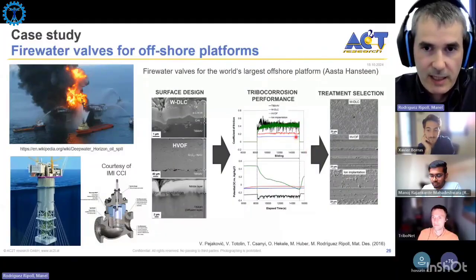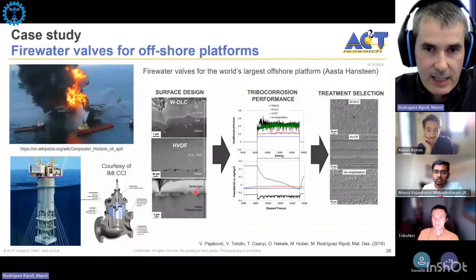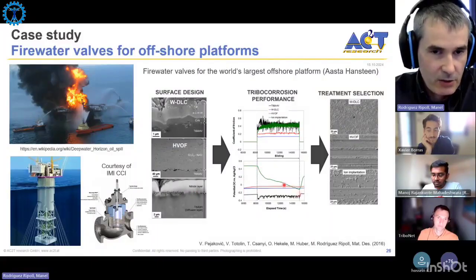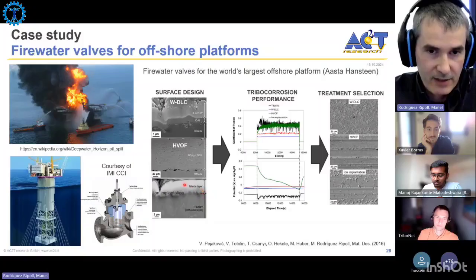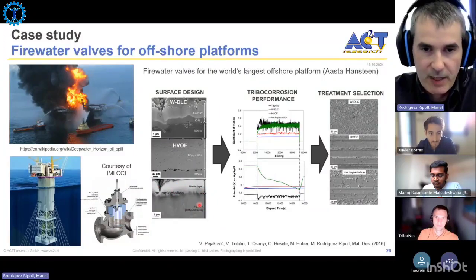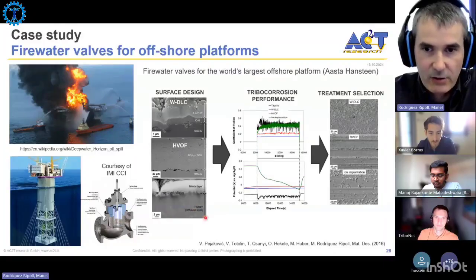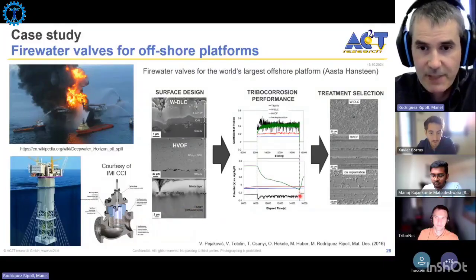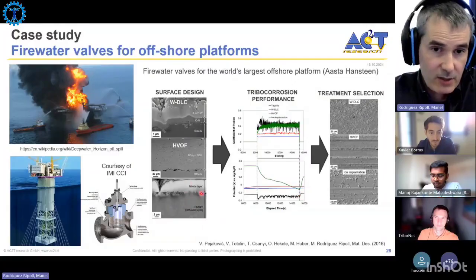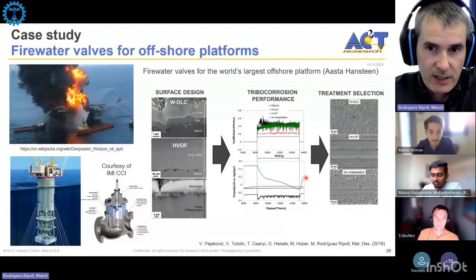For example, we see that the nitriding layer has a very high and very noble open circuit potential at the beginning of the experiment, but this potential dramatically decreases. The reason is that you break this nitride layer during the experiment, and then of course the material becomes less and less noble because you go into the diffusion layer, where you have titanium combined with some titanium nitrides. At the end of the experiment, we will not be able to repassivate because this layer is gone, destroyed. That's why the open circuit potential at the end of the experiment is lower compared to the initial one.